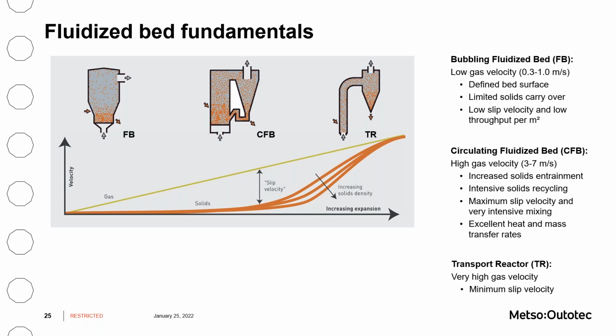Here we can distinguish between 3 reactor systems, which are all part of the Circored process. The bubbling or stationary fluid bed is characterized by low gas velocity and a sharp interface, which forms an apparent bed surface. The carryover is limited. Slip velocity and throughput are low, which means that the reactor system is well suited in case that prolonged residence time is required.